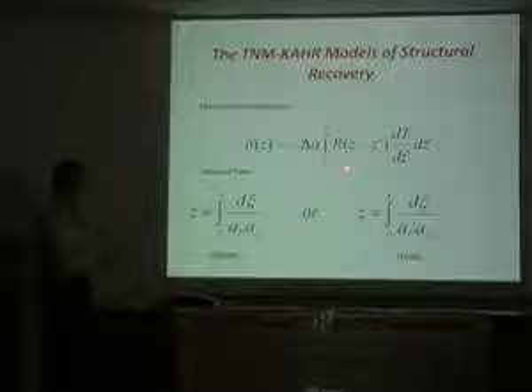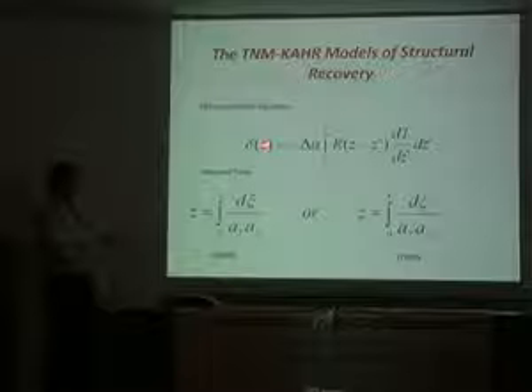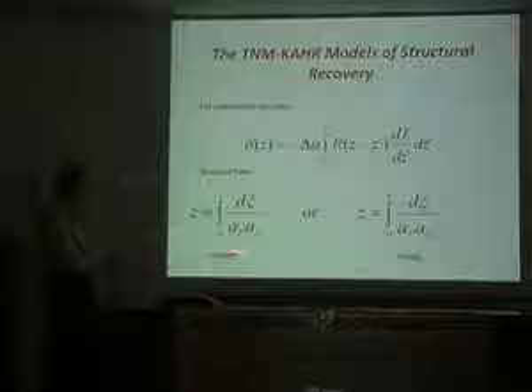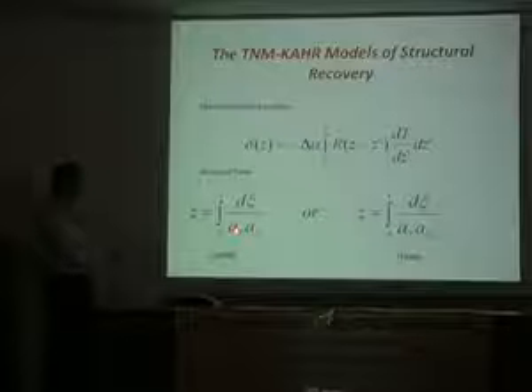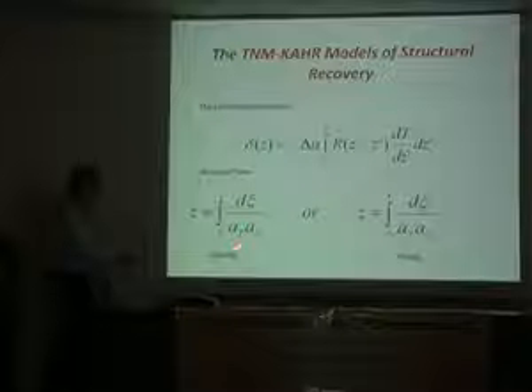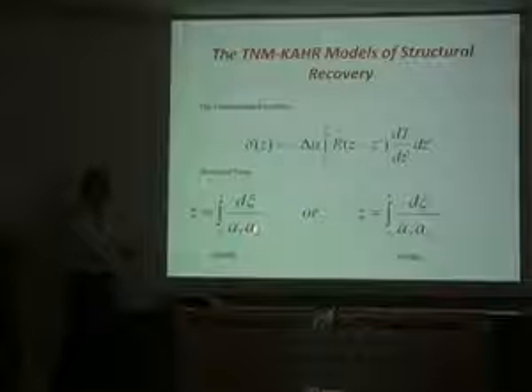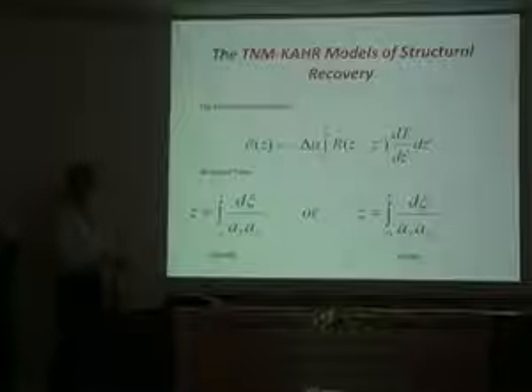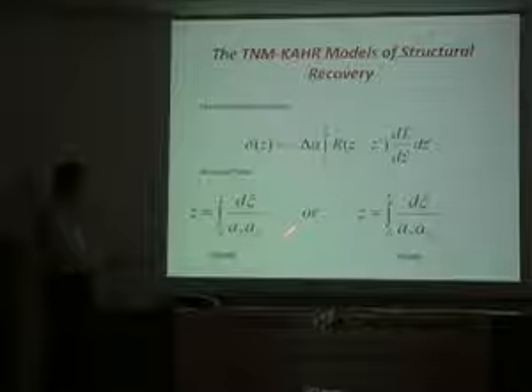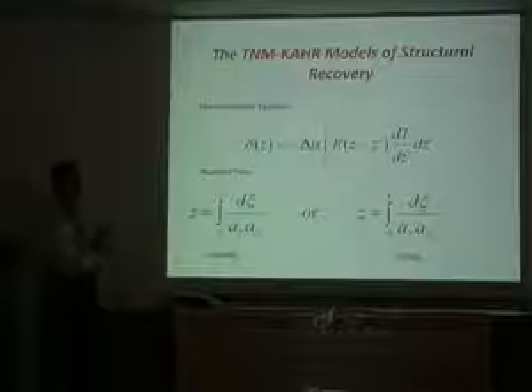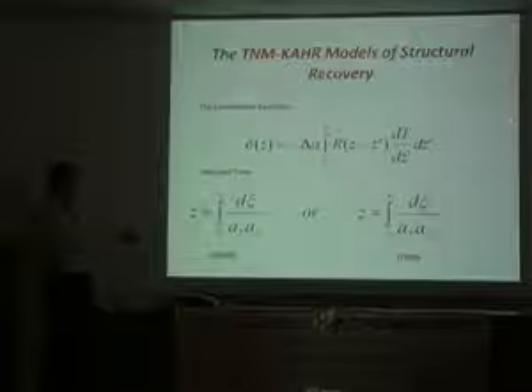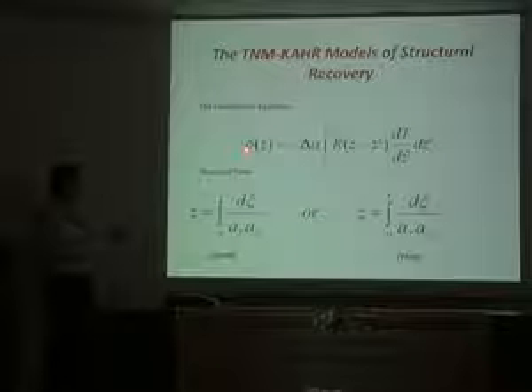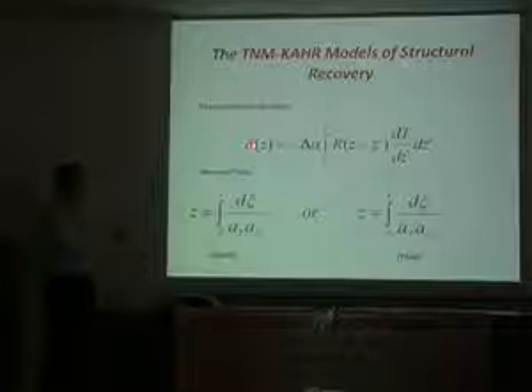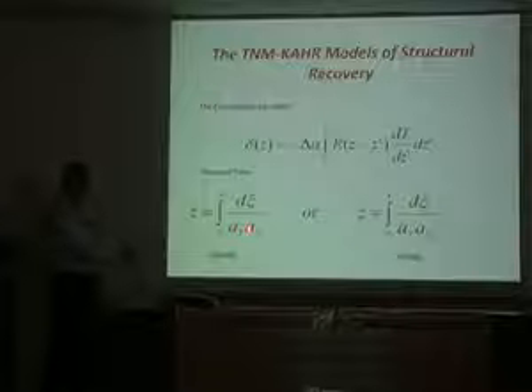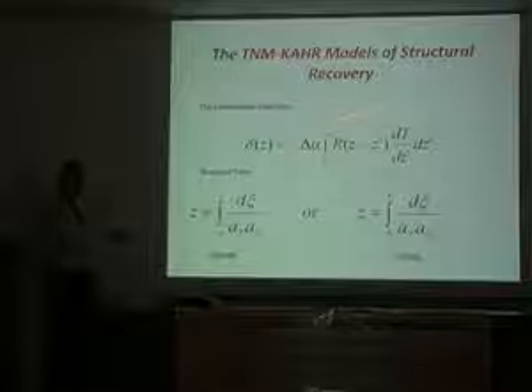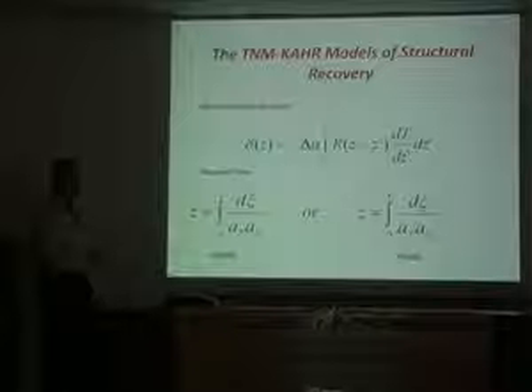And the reduced time, z, is defined this way. z is a function of just 0 to t of the temperature shift factor times the structure shift factor. And that changes the time scale during the experiment, right? So you have to reduce the time, and it's linear here. But the nonlinearity comes because delta depends upon itself, A delta depends on delta, through the reduced time. So that's the nonlinearity. Okay, so that's, I'm sorry?